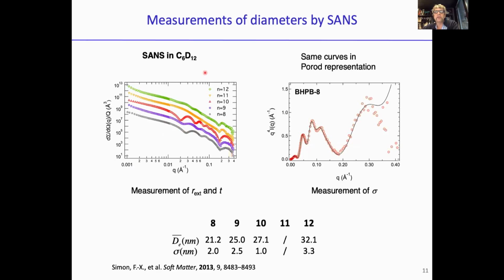This can be seen in another representation of these curves, which are basically the same curve. So this is the curve here, the same, but it's multiplied by q to the 4th. And here it's a linear representation. And in this representation, the oscillations of the cross section are enhanced. And you can see this is for 8 carbons, for 12 carbons. So you see the nice oscillations because these objects are quite monodispersed.